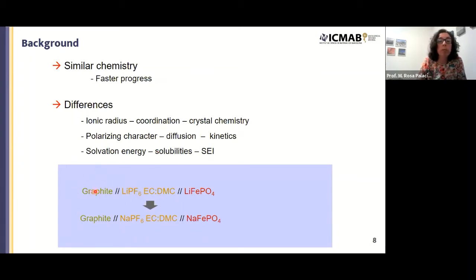So one example of those trends is here, as I was mentioning. Typically for the lithium-ion technology, one is using graphite, and the typical electrolyte is lithium hexafluorophosphate in a mixture of alkyl carbonate solvents like ethylene carbonate and dimethyl carbonate. And lithium iron phosphate, for instance, is one of the electrode materials which have been used commercially. So one could naively think that one can develop a sodium-ion technology just changing lithium hexafluorophosphate by sodium hexafluorophosphate and lithium iron phosphate by sodium iron phosphate. But this is not the case.